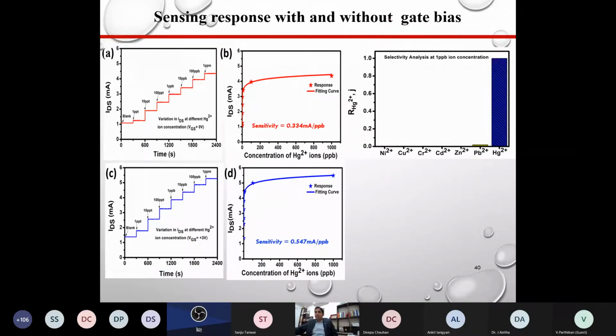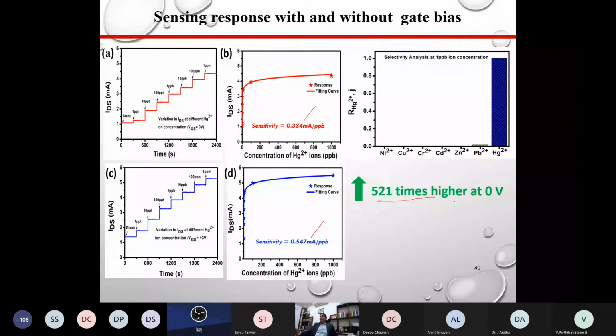So you can see this is at zero bias. This one is when we additionally used biasing, around 3-volt biasing. And by using this 2H and 1T phase, we can improve the sensitivity around 520 times higher than at 0 volt. So just by mixing these nanomaterials, because we have tried only the 2H phase and the 2H and 1T phase, we can explore many more materials for the different heavy metal ions. These are for these heavy metals.